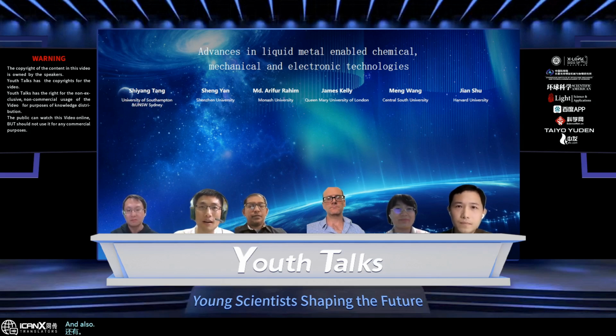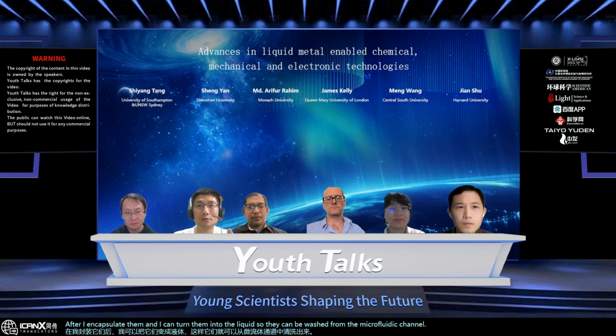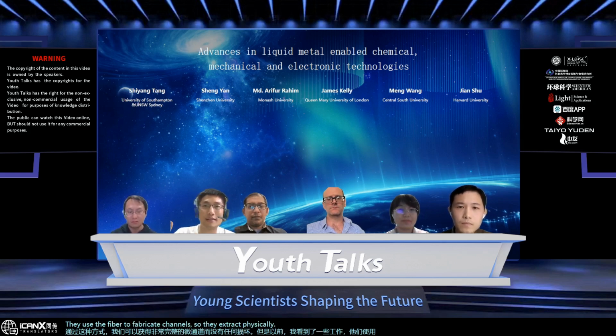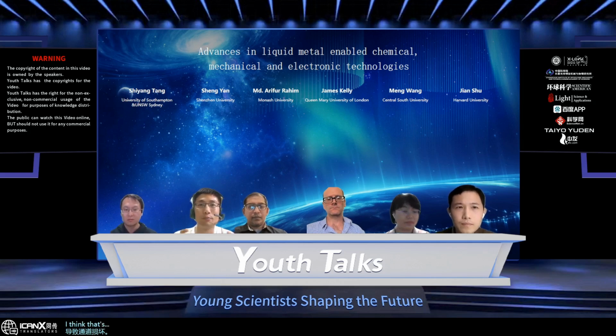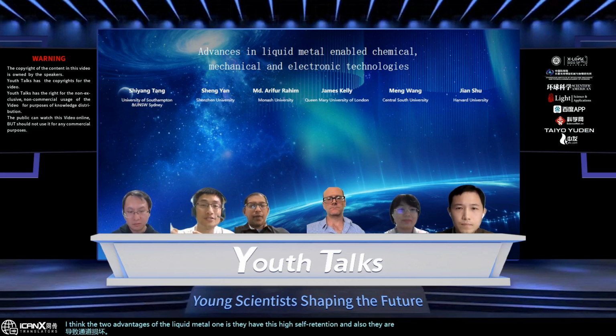Also, liquid metal has a phase change. For example, I can turn it into solid at low temperature, and after I encapsulate it, I can turn it into liquid, so it can be washed out of the microfluidic channel. In this way, we can get a very complete microfluidic channel without any damage. Previously, I saw some work that used fiber to fabricate channels, physically extracting the fiber from the channel, which causes damage. So I think there are two advantages of liquid metal: one is the high surface tension, and also it is a fast phase-change material.